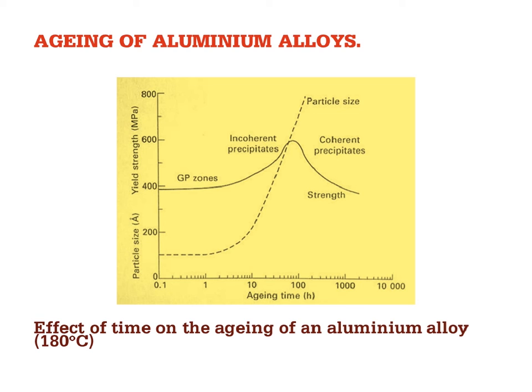We then cool it very quickly down to room temperature, and the copper is maintained in a supersaturated solution. It's a non-stable solid solution within the aluminium at room temperature because we quenched it down from a high temperature. If we then age it at 180 degrees C, let's say, we will then start to grow precipitates of copper aluminium 2. And you can see here the dotted line shows the average particle size, and after about 10 hours